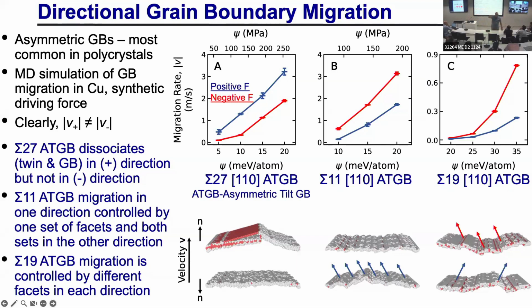By the way, if I take the stationary boundary, there's only one structure, right? So moving boundaries have different structures than stationary boundaries. If I switch to this boundary, the sigma 11 boundary, it turns out that as this boundary migrates, it's broken up into micro facets or nano facets. But in one case, the motion of the boundary is controlled by the migration of one set of facets. So if you have facets here, the boundary can move down by this facet moving this way, or this facet moving that way. Either way, it'll move down. Now, whether it's moving down or up, it switches which facets control the motion.